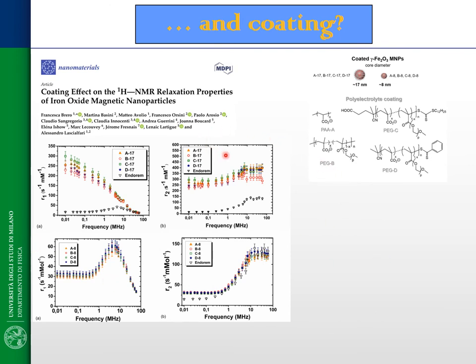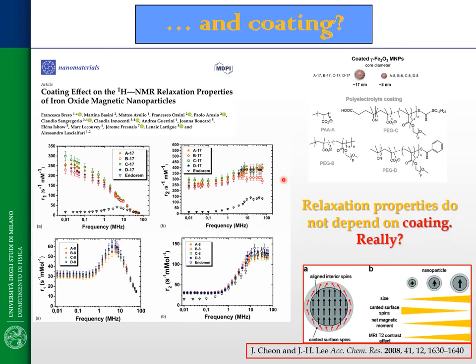In the last two years, we started to study the coating effect of magnetic nanoparticles. We started with maghemite nanoparticles of 17 and 8 nanometers, coated with different polyelectrolytes, as you can see here. For the moment, we have found that there is no evident effect produced by the different coatings. However, the coating effect can probably be seen only on the canted surface spins, so we need to go to a smaller size region to start to observe the effect of the coating, because only in that region does the quantity of canted surface spins become important with respect to the interior spins.